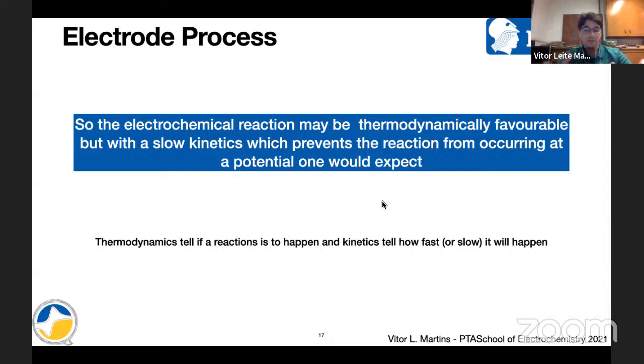So this is why the hydrogen reaction is not occurring in mercury, but it occurs in platinum. But you can ask me, this is the same reaction, so why does one have slow kinetics in mercury and fast kinetics in platinum? Because you have a different interface over there. Platinum metal has a different contact with the solution than the mercury electrode. You have some catalytic effects in the platinum that we don't have in mercury.